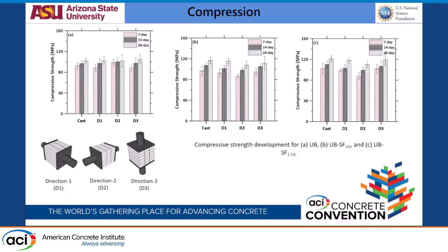What we observed is that, because of the rheological modification, we are still getting similar strength in the printed sample when compared to a cast sample. That was the first observation. The second major observation was that the anisotropy we see in 3D printed elements is nearly not present in these samples. I'll show you based on a calculation. Direction 1 is the compression along the print direction, direction 2 is along the filament direction, and direction 3 is along the build-up direction.